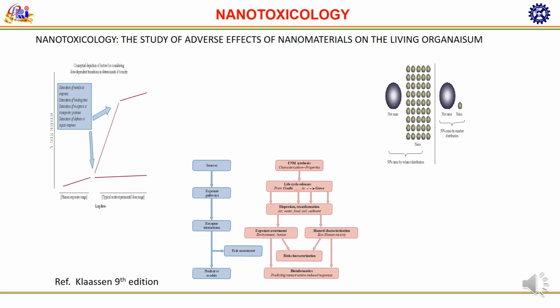For engineered nanomaterial synthesis, we have to do characterization of size, shape, surface chemistry, and solubility, and this determines the biological effect. Also the life cycle, from cradle to grave: nanomaterials can be released during production, use, and disposal. Dispersion and transformation: after release they undergo aggregation, dissolution, and chemical modification in air, water, food, soil, or sediment. Exposure assessment looks at how nanoparticles are present in the environment and how humans are exposed. Risk characterization combines exposure and hazard data to estimate actual risk. Bioinformatics can be used for toxicity prediction through nano-structure activity relationships.